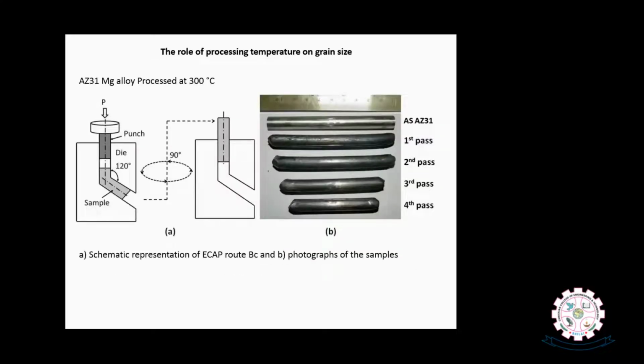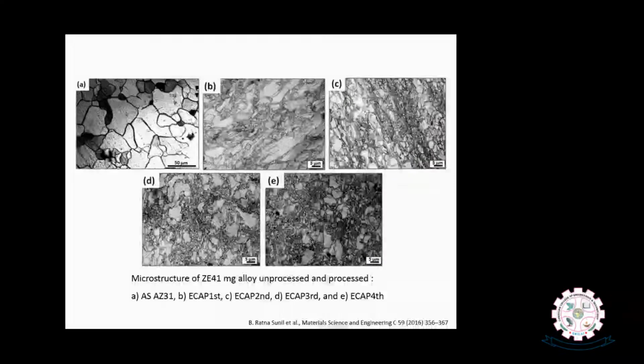And here you can see the same material, AZ magnesium alloy, when it is processed at 300 centigrade compared with the 100 degree centigrade in previous slides, where we have seen a total fracture of the material. But here you can see at the 300 centigrade, at a different number of passes, we have repeatedly processed the same sample up to 4 cycles. And you can see successfully the material is plastically deformed and no fracture was observed. The corresponding microstructures also show large grains as well as combination of very fine grains. The development of these large grains, as I explained, is because of the prolonged exposure of the material at 300 centigrade close to the annealing temperature, which triggered the grain growth, and whatever the grain refinement effect that we observed after first and second cycles has been lost up to some level in third and fourth cycles.